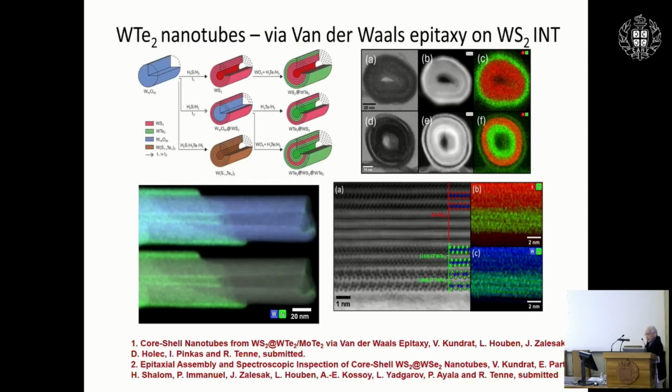And there are other techniques and other technologies to produce core shell nanotubes. For example, if you want to use chlorides, many of the halides or hydroxides are layered compounds, and you can do the reaction in the presence of, for example, molybdenum chloride, and you can get molybdenum chloride layers coating the tungsten disulfide, or for that sake, you can also take carbon nanotubes. And there is a paper just published on that, using chromium iodide, which is also a very important magnetic quantum material, coating carbon nanotubes.